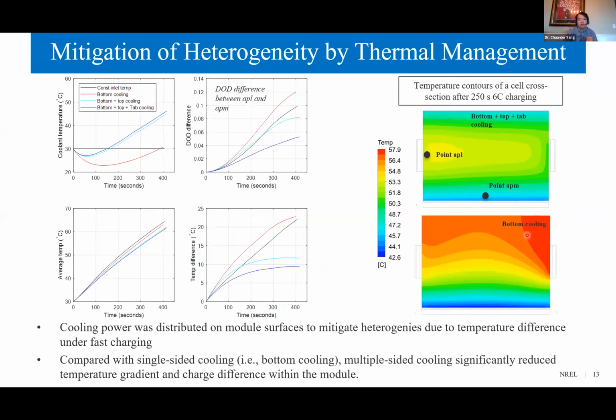For example, before there was only bottom cooling. Now, if we compare it with top cooling and tab cooling, here is what it looks like. As long as the heat is evenly distributed to its surroundings, significant heterogeneity mitigation can be achieved by cooling the cell on multiple sides, as shown.